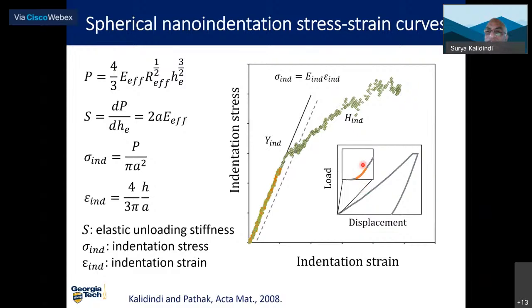But if you identify that elastic portion right, and you apply Hertz theory, the equations here are nothing but Hertz theory. There is absolutely nothing there other than Hertz theory, and a generalization of a definition of strain. That's the only thing there is on this side. But if you adopt these 4 equations, and you identify the elastic portion, you can convert the load displacement curve, which looks very smooth, and where you can't tell by looking where the elastic portion or plastic portion is. But if you do the analysis right, you can get a beautiful looking stress strain curve. You can see the elastic portion, you can see the plastic portion.